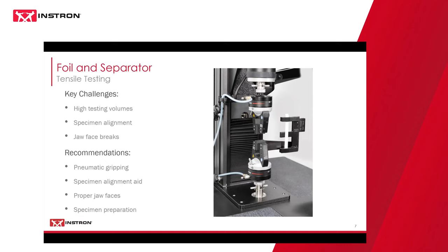And then for both foil and separator film, we've been seeing tests in the range of hundreds per shift for quality control. So when you're considering high volumes like this, you want to be considering things like pneumatic gripping, and proper fixturing or proper aids are essential to ensure your throughput and your repeatability are met. This is a key area for pneumatic gripping because it has less operator dependence and no time wasted with manual gripping for each specimen. I can't imagine trying to manually clamp down 300 or 400 specimens in an 8-hour shift. I think I would go insane.